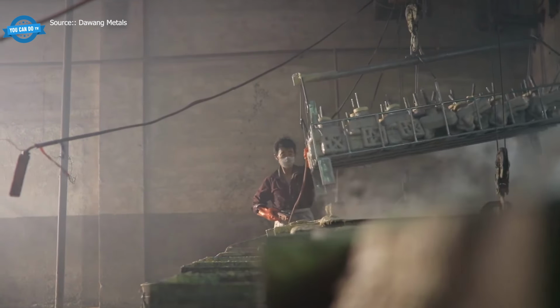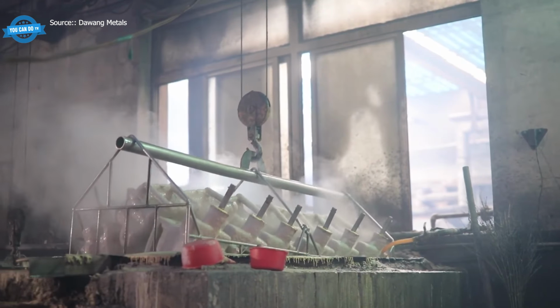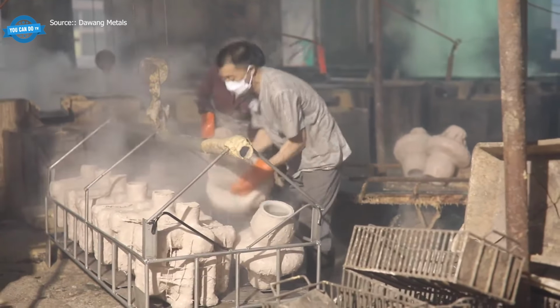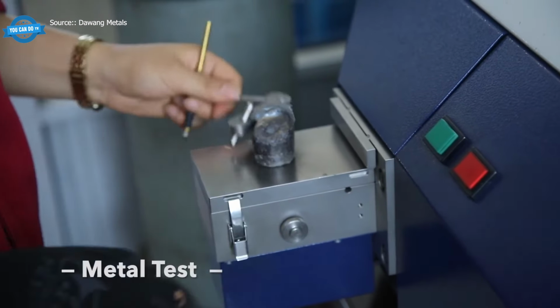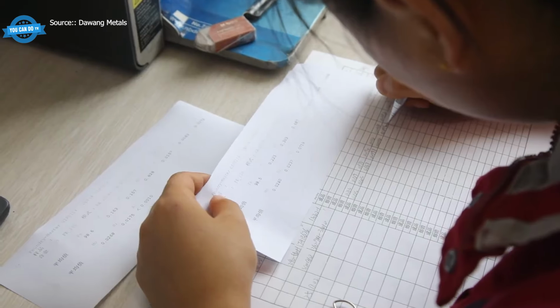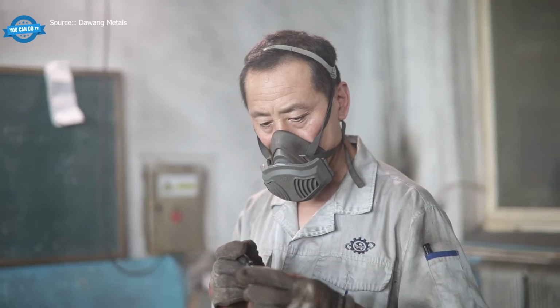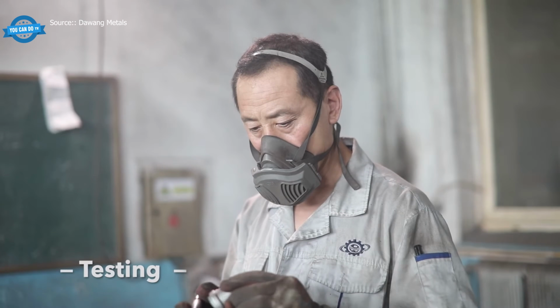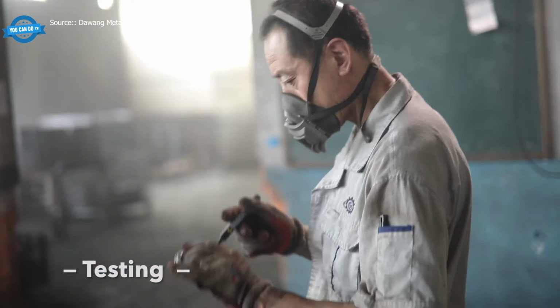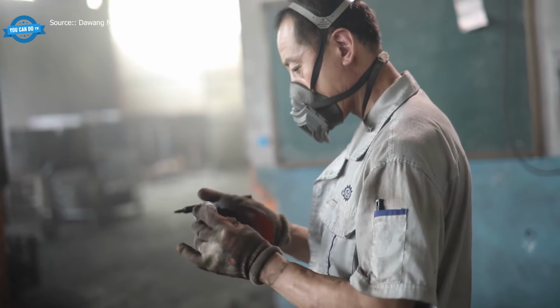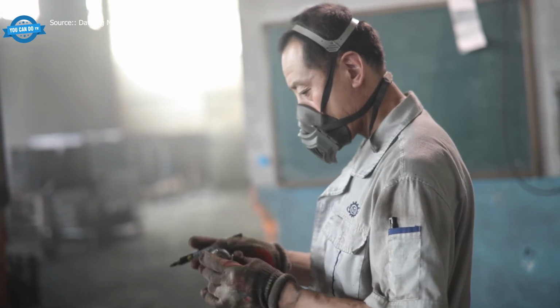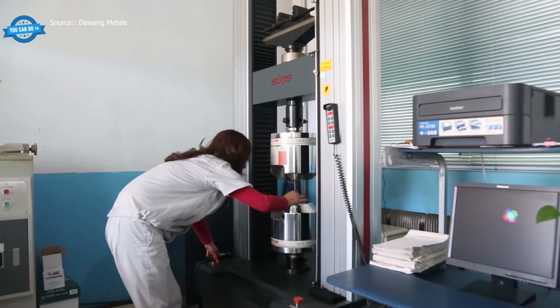Tensile tests pull samples until they snap to confirm the alloy is what it claims to be. A casting can pass every visual check, and still fail the pull test because visual checks do not see what is happening between the grains. Radiographic and dye penetrant tests hunt for cracks and porosity the eye cannot catch.